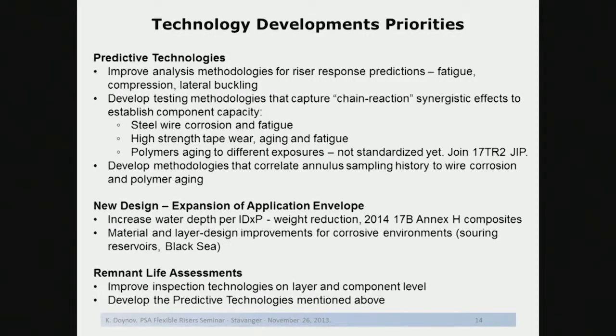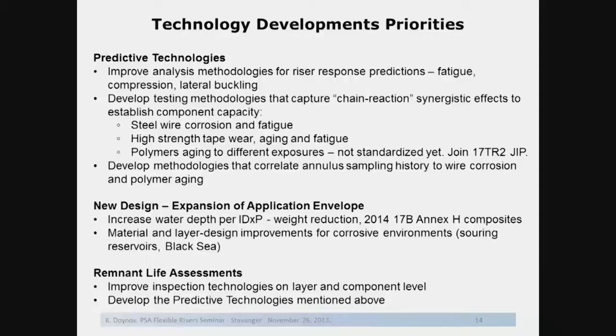Developing testing methodologies that capture chain reaction of synergistic effects to establish component capacity, as I mentioned, for wire corrosion and fatigue, high-strength tape wear aging and fatigue, polymers aging to different exposures, which are not standardized yet. That's what one mentioned, that Force Subsea is going to be managing this JIP for 17TR2, which is going to stay with the same number. It's just going to be renamed to aging of polyamides as opposed to aging of PA12. We have joined that and recommend everybody else to do so if you haven't done so yet. And finally, to develop methodologies that correlate annulus sampling history to wire corrosion and polymer aging.